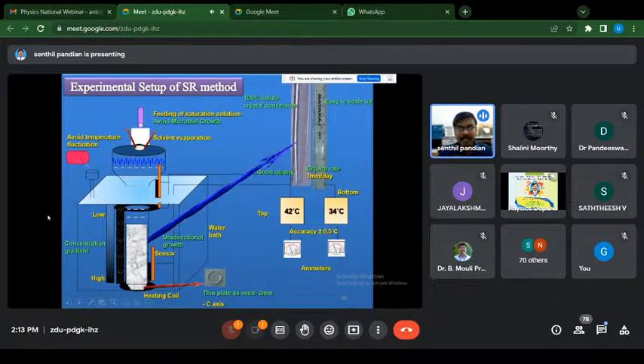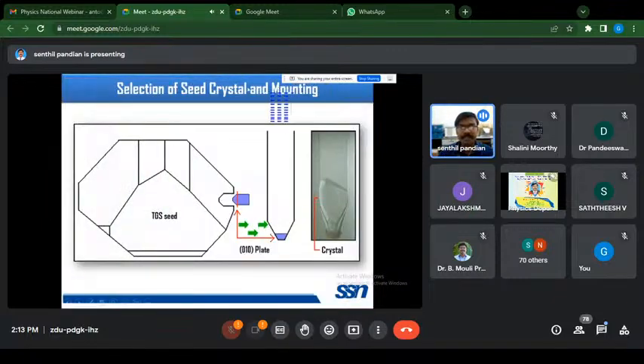So this is the complete schematic diagram animation figure of the experimental setup of this SR method. All the crystals we have grown are based on this setup only. So this is the selection of seed crystal, cutting and mounting. This is the TGS seed crystal. Using morphological measurement, single crystal X-ray diffraction, you have to identify the direction or phase of this grown crystal. So this is the polar B direction, 0 1 0 direction. Using a fine hacksaw and blade, we cut the crystal like this, make a very small thin plate like a seed crystal, and mount it at the bottom of this glass ampoule, and then pour the saturated solution.